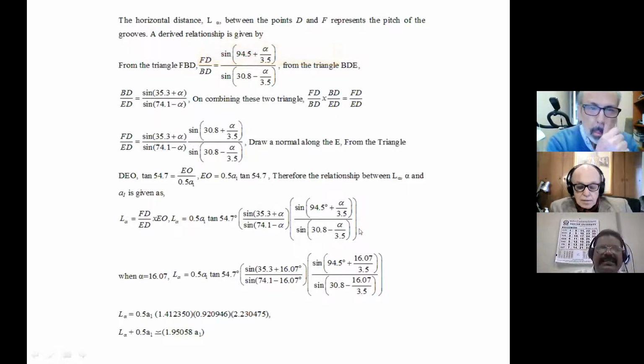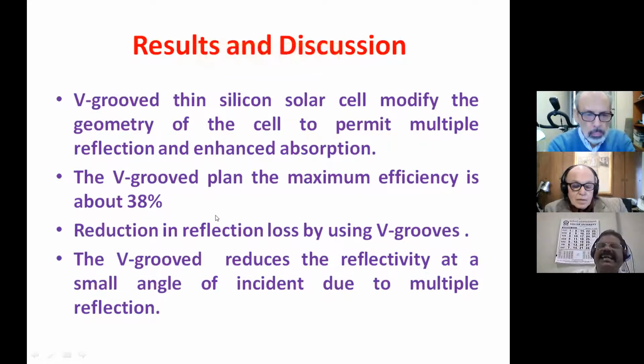So we have calculated lengthy equations for identifying the distance required to align the micro lens above. The optical path is also calculated. It is 2 times the width of the V grooves we have identified, and we have also measured the quantum efficiency of the V groove. The comparison is planar cell without microlens, V groove without microlens, planar with the microlens, and V groove with the microlens. The highest quantum efficiency we achieved is for the V groove with the microlens structure. So this result says that the V groove thin silicon solar cell modifies the geometry of the cell to permit multiple reflection and enhance the absorption.